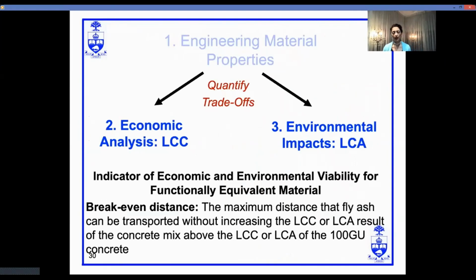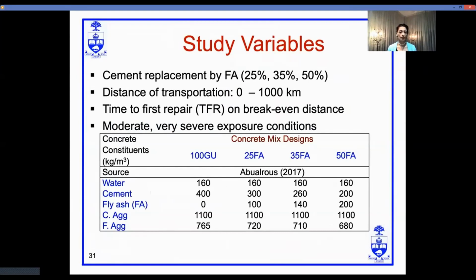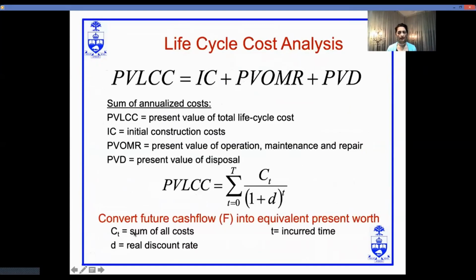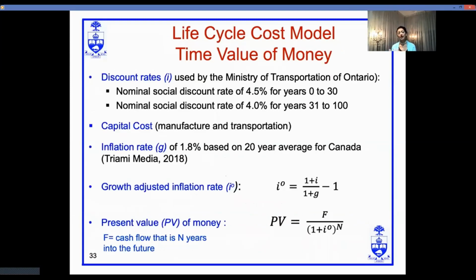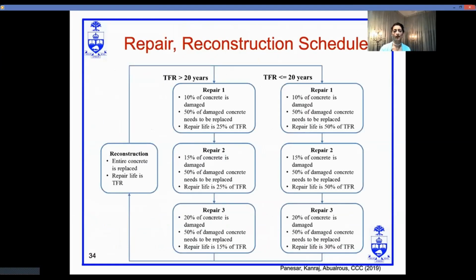So once we had established our acceptable concrete material properties, then we needed to look at economic viability and the economic and the environmental aspects. The indicator we're using here is the break-even distance, which is the maximum distance that fly ash can be transported without increasing the cost or climate impacts in comparison to the 100% general use scenario. So this just shows some of the mix designs we used, containing up to 50% fly ash. The life cycle cost analysis was done with a fairly straightforward present value of total life cycle cost approach. This slide just shows the discount rates, the inflation rates, et cetera, that were used for the analysis.